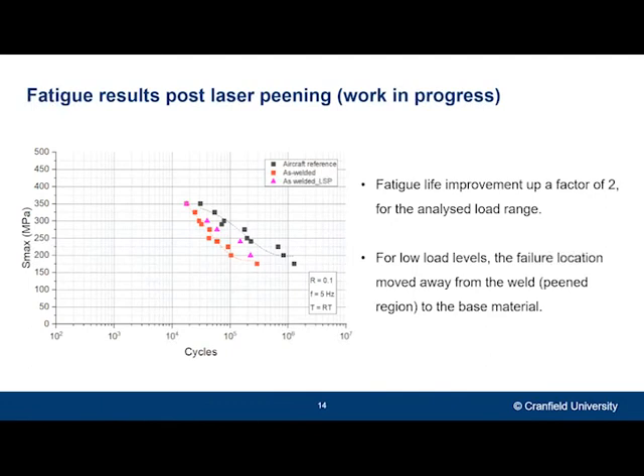Finally, here are our fatigue test results after peening with the parameters that I showed you, for as-welded samples with no defects. You can observe that there is a life improvement of about a factor of 2, but for the lower load range that I tested. You may be surprised about the lack of improvement for the higher side of the spectrum. However, you can see that the stresses are quite high, about 350 megapascal, which is significantly high when we compare it to the compressive stress that we were able to achieve with the peening treatment.